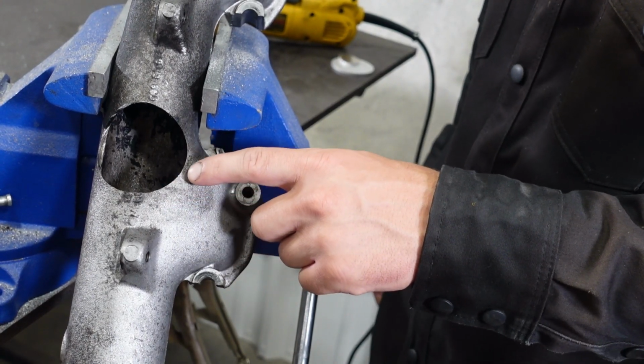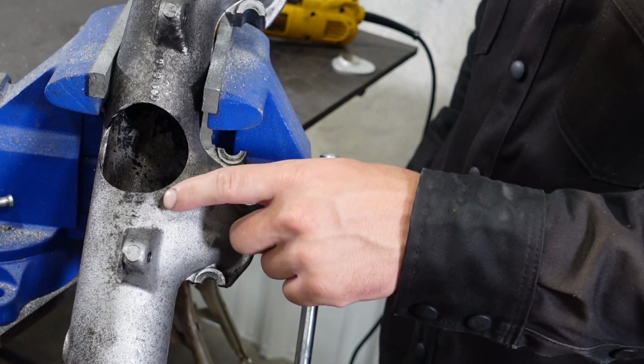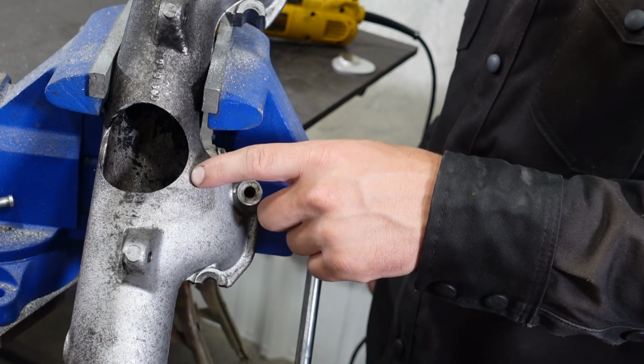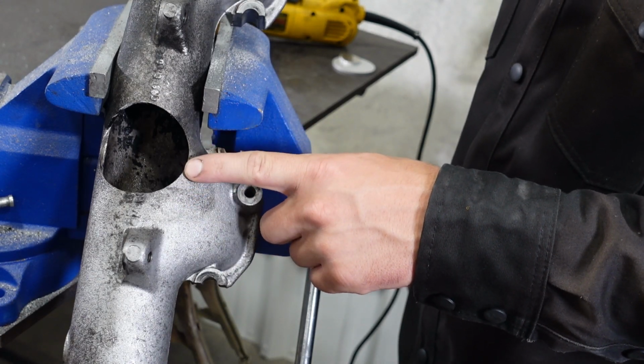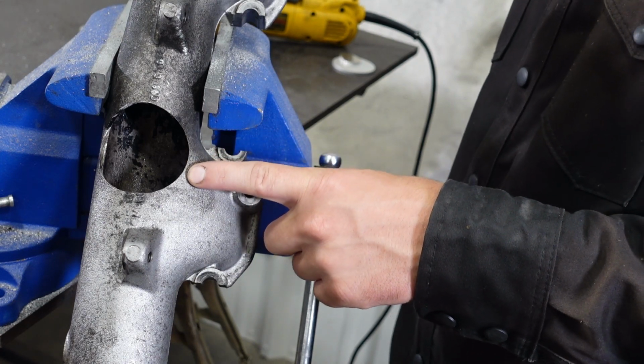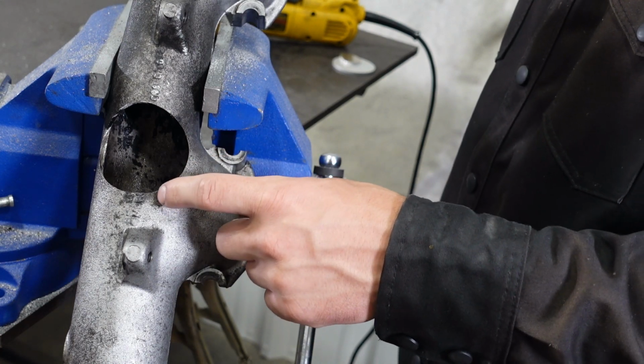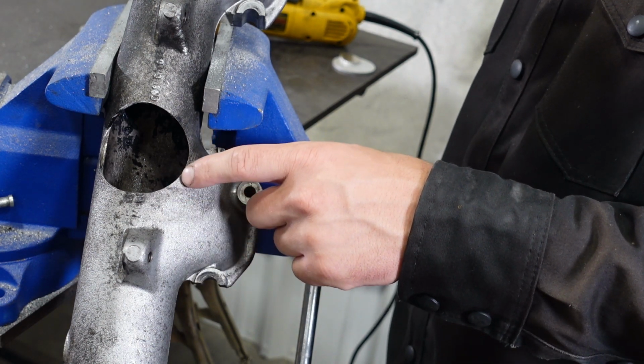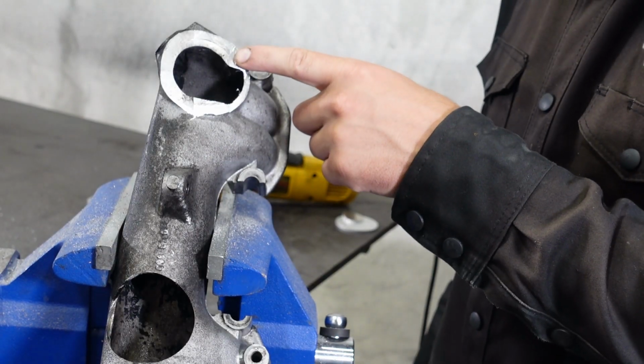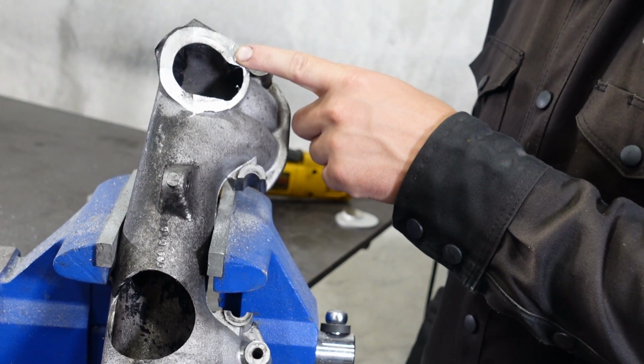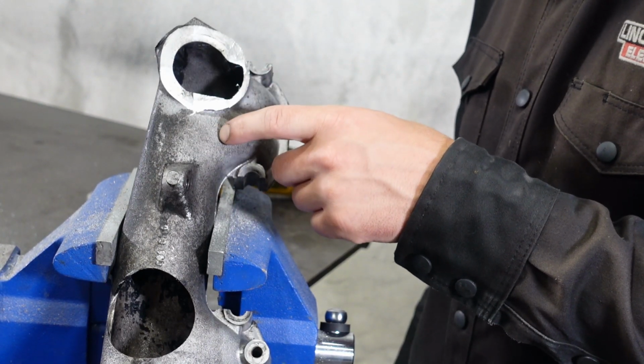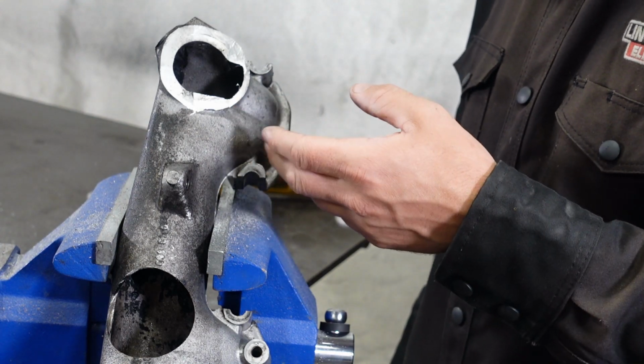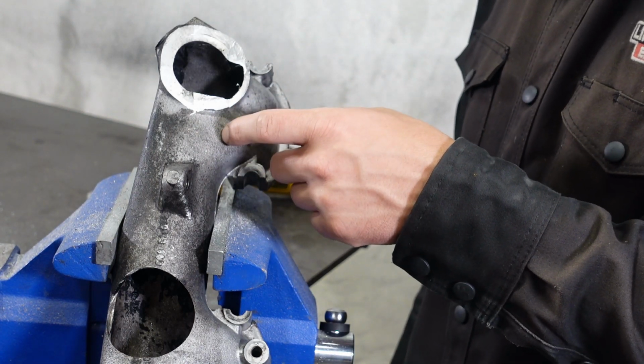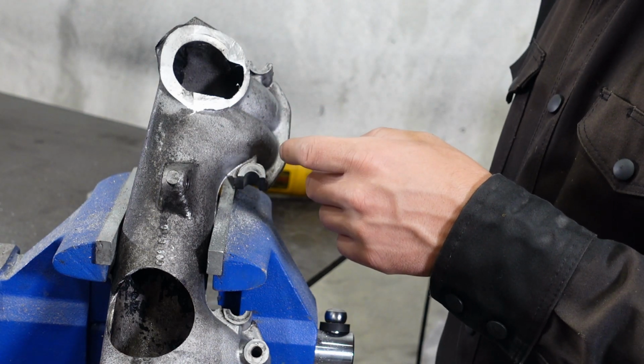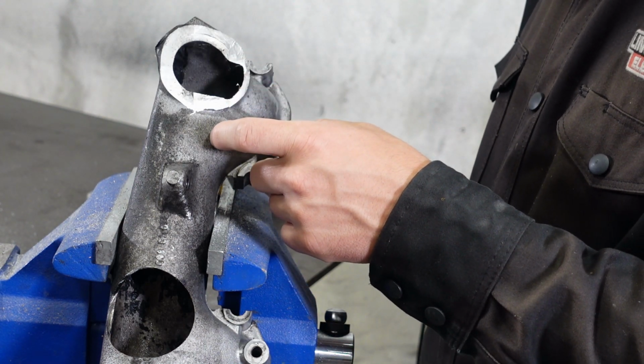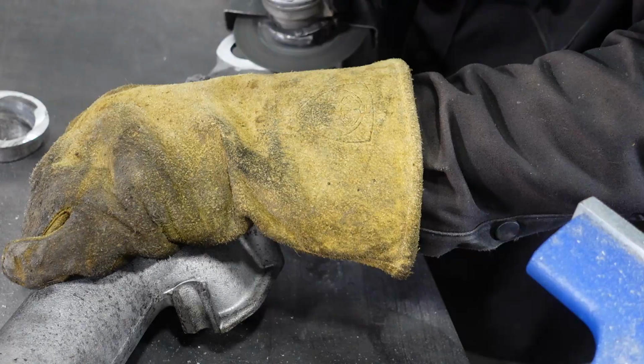And then lastly, I'm gonna take the cutoff wheel to this cast surface, and I'm gonna remove that very top layer. If you try welding to this cast surface, your weld's gonna bubble up, you're gonna get a lot of porosity. I found that simply taking a cutoff wheel and removing this cast top surface until it's smooth and shiny like this is enough to give you a decent weld on this cast aluminum intake manifold. This isn't the case with every type of cast aluminum, but every type of cast has different alloying elements in it. This happens to work just fine by removing that top surface.